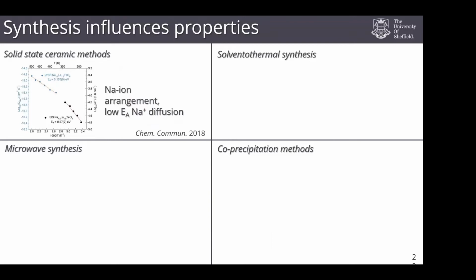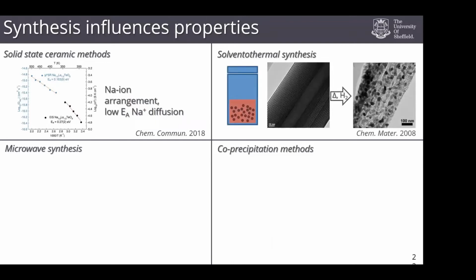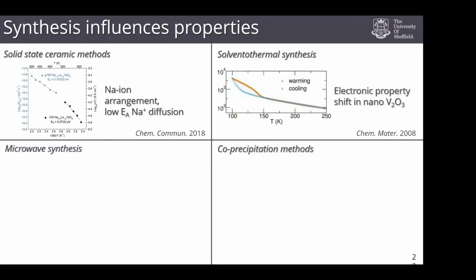You can also think about, how do I change the size and shape of things? So I can sometimes use a liquid in a solvothermal type synthesis. And this is showing you a liquid-based reaction where we're able to make nanoscrolls of a vanadium oxide material. And by just changing the reduction conditions, we can form very small nanoparticles, in this case of V2O3. And that can change the electronic properties of these materials because the size has a big effect on the properties.